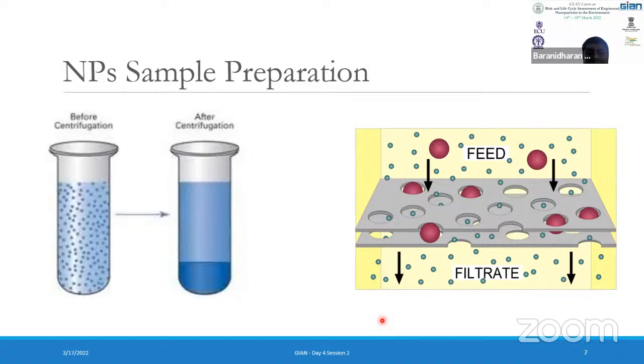Centrifugation is considered one such easy step and the simplest approach to isolate the particulates, mainly the suspended material, from the aqueous suspension, as well as to separate nanoparticles from the dissolved species. However, if you keep increasing the rotation, high centrifugal forces and very long durations are required, and removal of nanoparticles from supernatant containing dissolved species is very tough. Even at very high rotation speed, sometimes it is not possible to remove those tiny particles from the suspension.